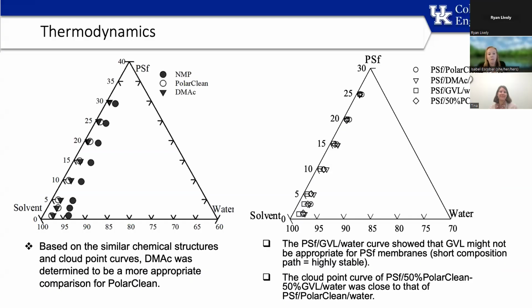So as the first step, we usually do the RED values, and then we go into the thermodynamics, and we do our ternary phase diagrams. I am not going to go through all of the thermodynamics of this. As much fun as it would be to go through all of the thermodynamics of this, we just want to look at some very specific similarities. For the first one here, we looked at just Polar Clean, polysulfone, and water, and we saw that Polar Clean and DMAC pretty much followed the same lines and behaved very similarly in those cloud point curves in the thermodynamics development.